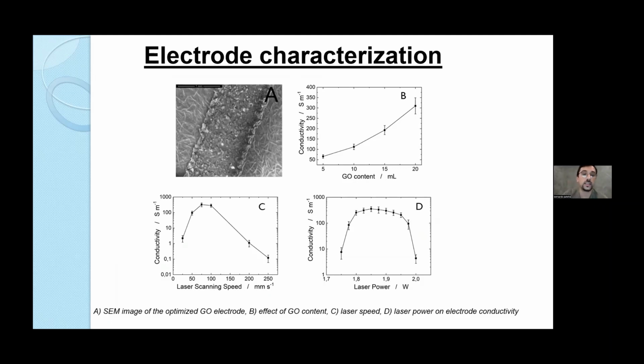As we can see, figure A shows the SEM image of the electrode. This line is the reduced part of the graphene oxide, while on the right side of this line, there is the unreduced graphene oxide. And as it's possible to see, there is a very different morphology, and in the reduced part, there is a very rough surface.